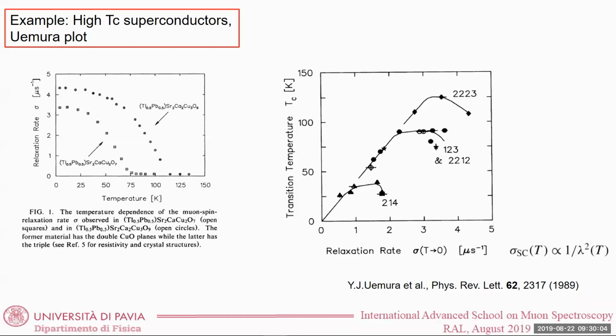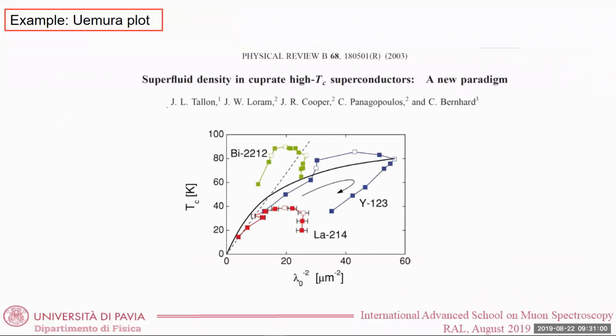Uemura first proposed this plot where one can plot Tc as a function of sigma, the transverse relaxation rate, or if you want, as a function of the inverse of the square of the lambda penetration depth, which is basically proportional to the density of superconducting carriers. And then, since there is some linear behavior, there started to be some speculation about proportionality between Tc and the Fermi energy for a 2D electron gas, since for the 2D electron gas the number of superconducting carriers is proportional to the Fermi energy. But anyway, it's a nice way to analyze the properties of superconductors. And this you can study well if you do MUSR, not if you do NMR. Of course, more recently there have been different studies of this system that have put some remarks on this Uemura plot.